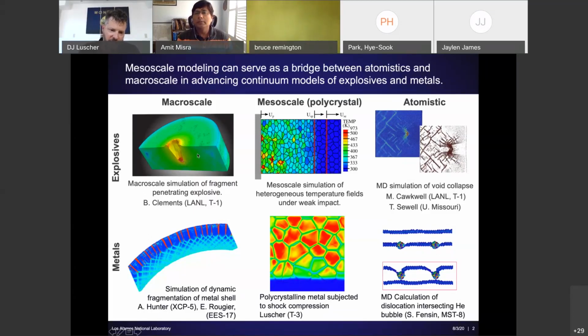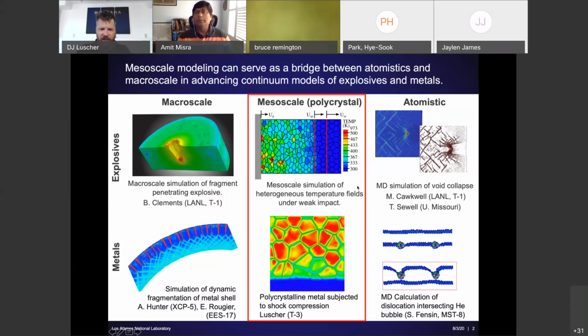For example, this image in the upper left is showing the simulation results from a fragment penetrating into an explosive, and we could imagine that if you zoom in close enough, you would see that features such as pore collapse at the atomistic scale present localized shearing deformations and localized heating that can contribute through the mesoscale type of simulations to the overall response that's important even in the macro scale. And so we view this in-between scale, where microstructure is important, as a bridge between those two.